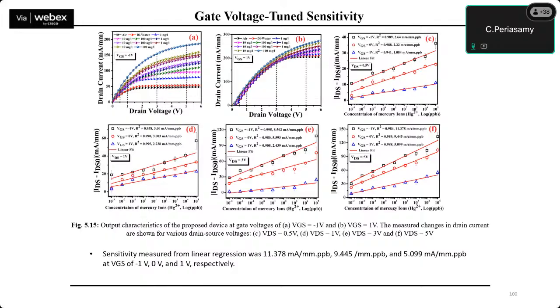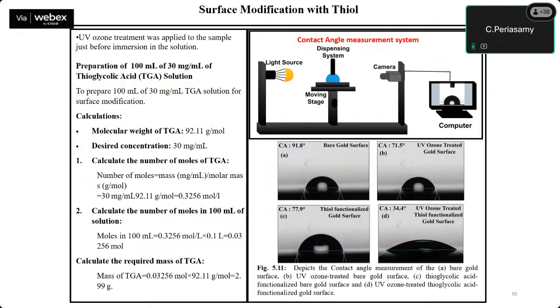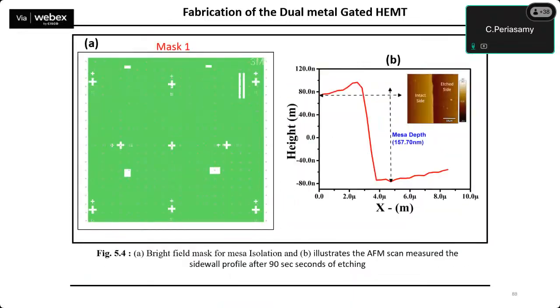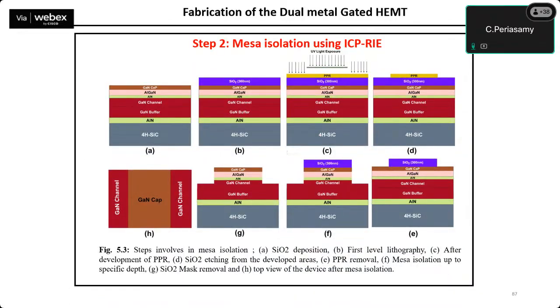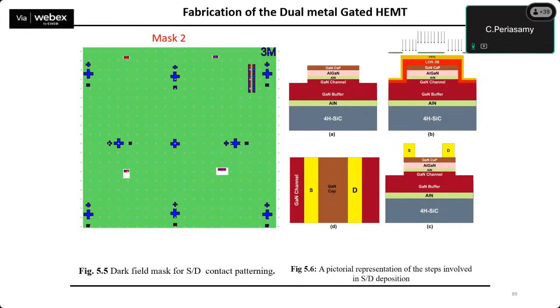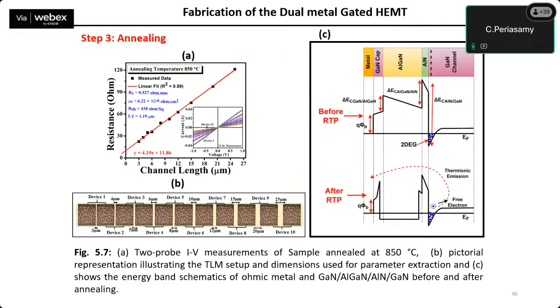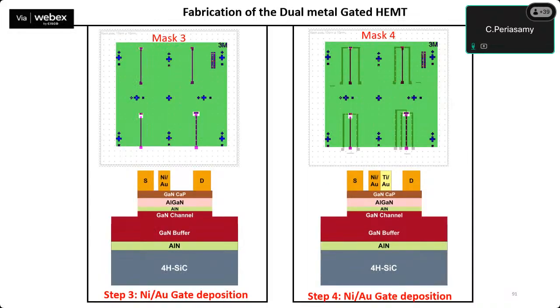To detect mercury ions, for this proposed structure we used the APTES functionalization layer. One can use it to detect heavy metal ions like mercury or lead or any other metal. One can use lead or SiO2, but in this study we have used the APTES functionalization material.